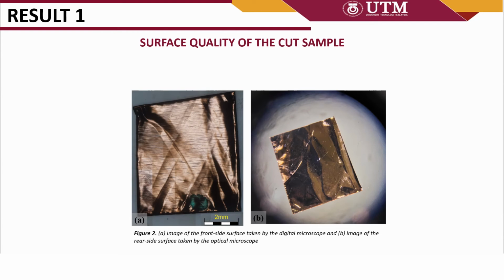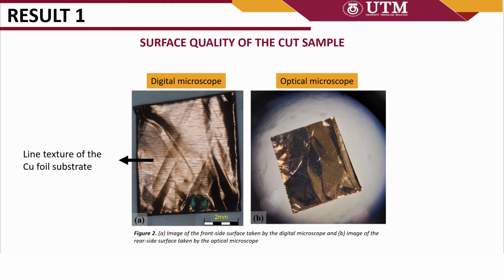Figure 2 shows the image of the front side surface taken by digital microscope and the image of the rear side surface taken by optical microscope. From the results, the line texture of the copper foil substrate can be observed in both the images, although that with the optical microscope was not clear due to different magnification.